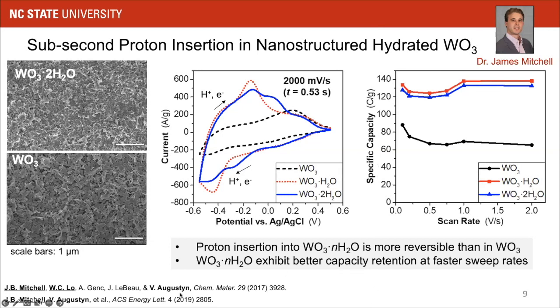And we took a look at various form factors of hydrous tungsten oxide. Sometimes they were slurry electrodes, sometimes they were thin films. This is the result from the thin film study. And what we always saw was that proton insertion in our hydrous materials was more reversible than in the anhydrous tungsten oxide, with better capacity retention at fast scan rates.